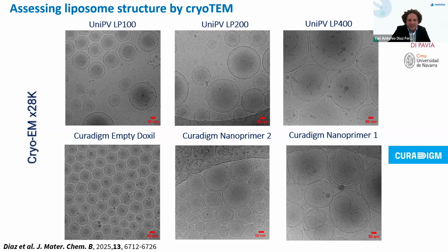All these liposomes are prepared using the classical thin film extrusion method. And what you can see is that the morphology, and also the internal morphology of the liposome, is preserved, and you can count the single lamella layers that are formed there. I hope the resolution of the image is good enough on the screen that you can see these are sometimes single lamellar structures, and sometimes multiple lamellar,